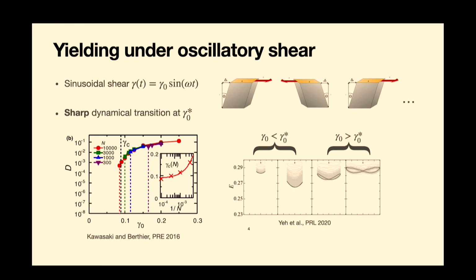Okay? You see here, you basically have hysteresis, so the system is dissipative. Even in steady state, in every cycle, you dissipate energy because you're performing work, as you can work out from the sort of integral inside that closed loop. Okay? So this is another way of visualizing that same transition as here. The states that don't diffuse are basically elastic. The material always comes back to the same configuration, essentially. And the states above that amplitude, they're fluidized. There's dissipation in every cycle. The system is essentially flowing.